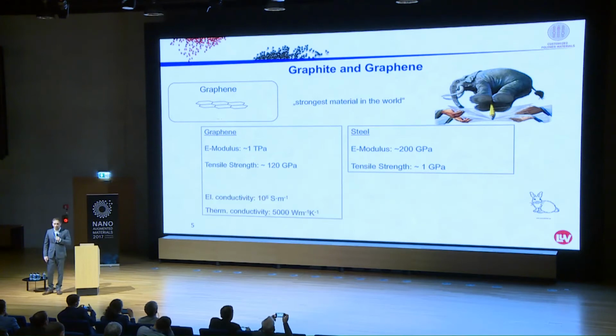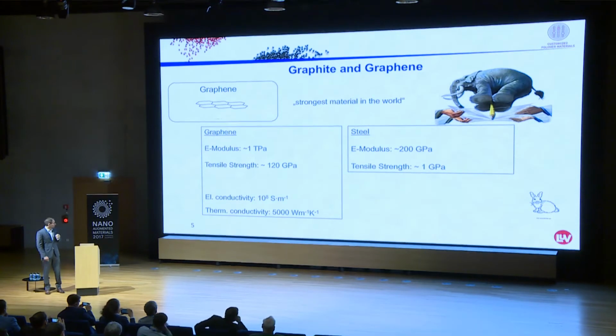But also in conductive matters, graphene has really outstanding properties. It has an electrical conductivity of 10 to the power of 6 Siemens per meter, and a thermal conductivity of about 5,000 watts per meter Kelvin. So here it outperforms one of the best conductive metals, silver, about 10 times.